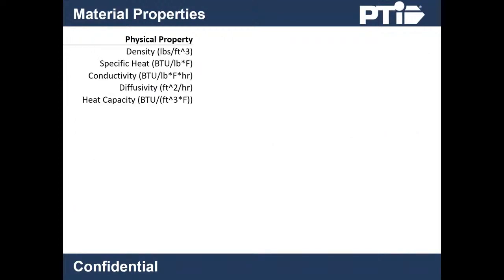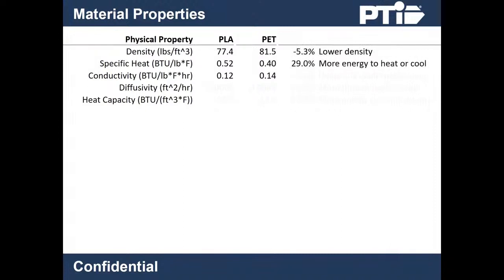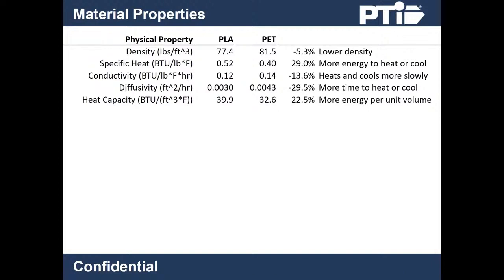Let's take a quick look at some of PLA's thermal properties as compared to PET. Please don't get lost in the US units. The only important takeaway from this comparison is the relative difference between PLA and PET. PLA has a lower density, but a much higher specific heat, which means it takes more energy to heat or cool it. PLA has a lower thermal conductivity, which means it takes longer to heat and cool. But when you calculate diffusivity, the result becomes significantly greater time to heat or cool. When we calculate volumetric heat capacity, we still have significantly more energy to add or remove in the process.